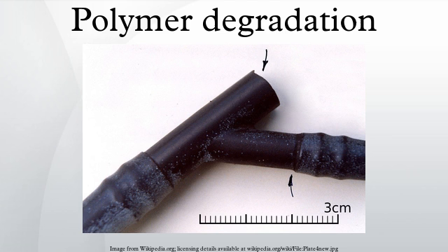The cracks are always oriented at right angles to the strain axis, so will form around the circumference in a rubber tube bent over. Such cracks are dangerous when they occur in fuel pipes because the cracks will grow from the outside exposed surfaces into the bore of the pipe, and fuel leakage and fire may follow.